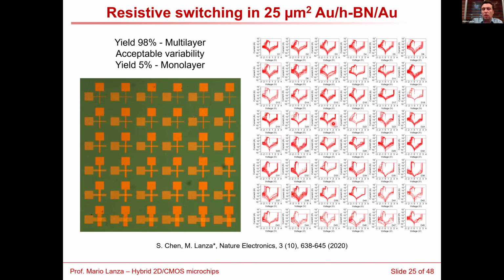When we repeat the same process using monolayer hexagonal boron nitride, we observe that most of our devices, like 95%, are shorted and only 5% work well. Of course, this can be improved, and there are some groups that have tried monolayer hexagonal boron nitride as dielectric, and they observe higher yield than us, which means that they are better in terms of fabrication than us. However, still with multi-layer, using the same process, you can get much higher yield for memristive application.